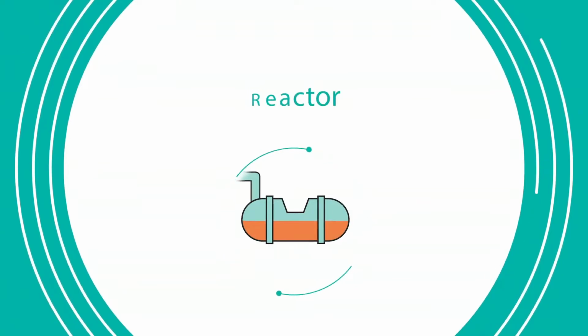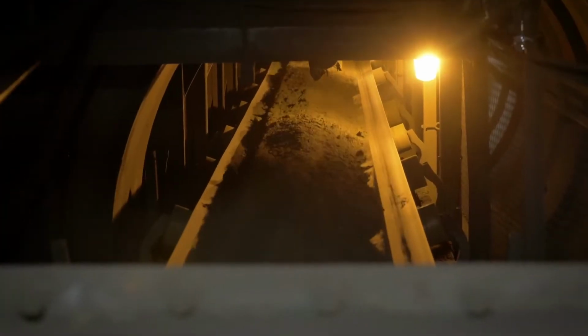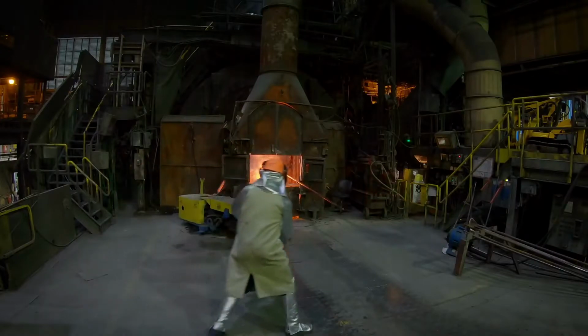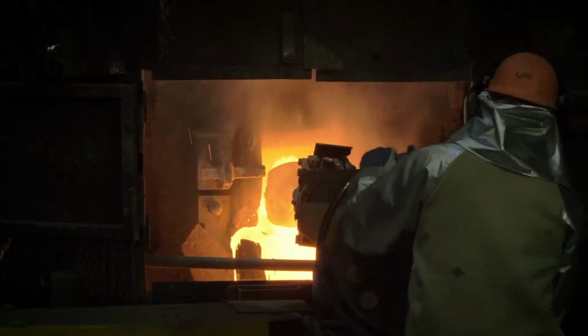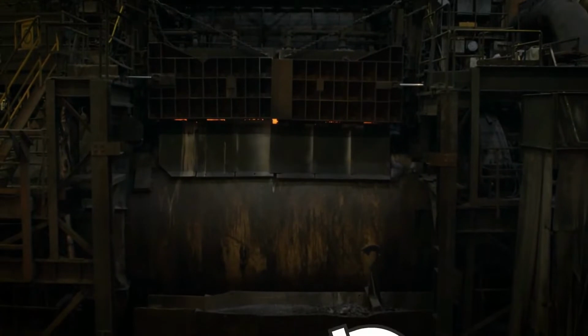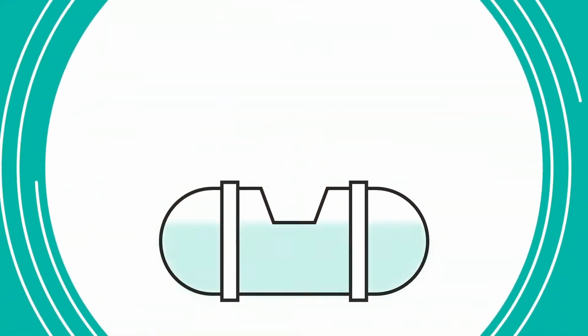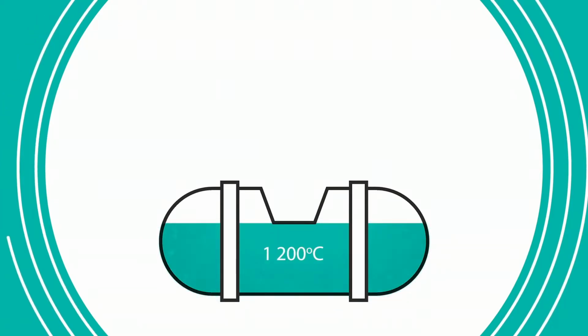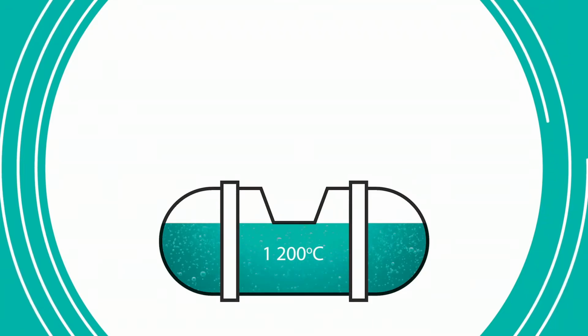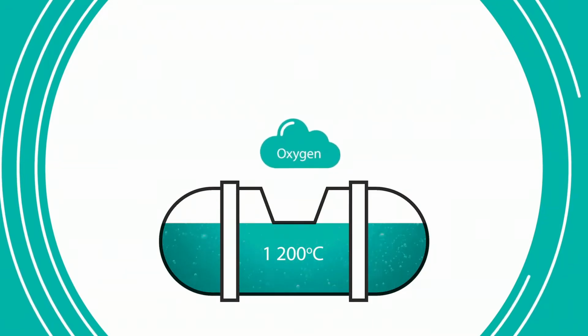The recyclable material is now ready to be taken by conveyor and fed into the Noranda reactor, a technology developed by our research and development team in 1973. Materials are projected into the vessel by a high-speed slinger. The vessel is heated at 1,200 degrees Celsius, making it possible for materials to liquefy. The purifying process consists of injecting oxygen-enriched air.